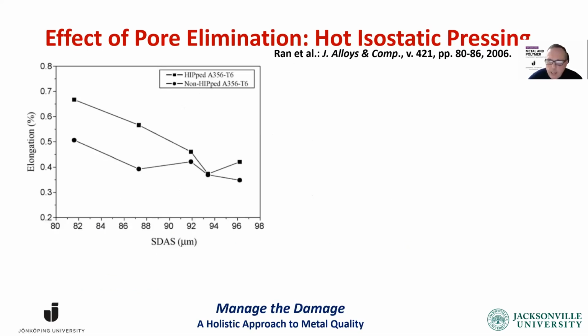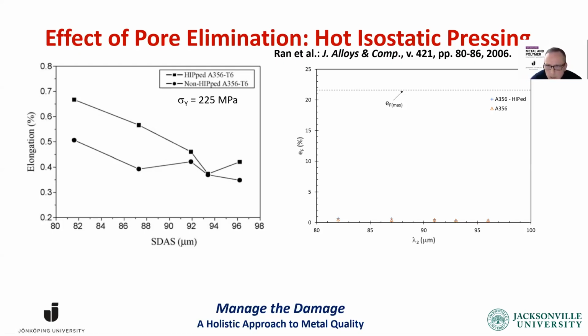Okay, how about another process, hot isostatic pressing, where the metal is heated to about 500 degrees and we apply some pressure on it. Here's what I could find from the literature. When you look at this, there seems to be some improvement between hipped and unhipped, but when we pay close attention to the y-axis scale, we notice that it's really, really zoomed in. And if we zoom out, as I do, on the right-hand side, you're going to see the data points all the way at the bottom, which basically overlap. And I give you the ductility potential, which is about 22% at that yield strength of 225 megapascal. And the quality index that we end up with is 2 to 2.5%.